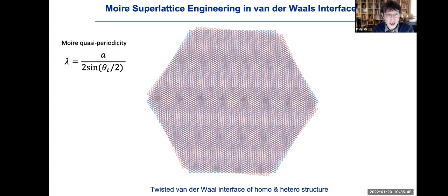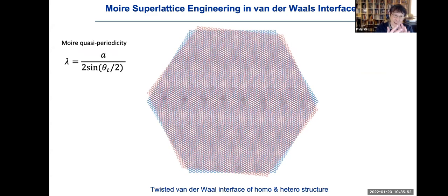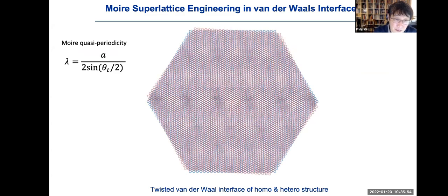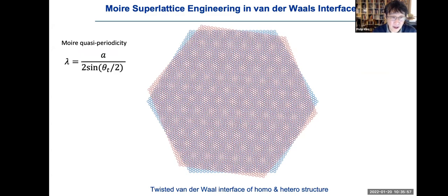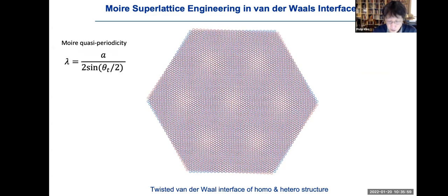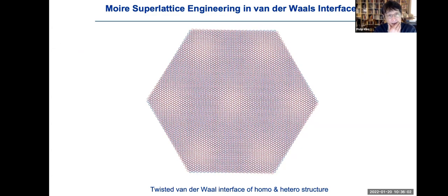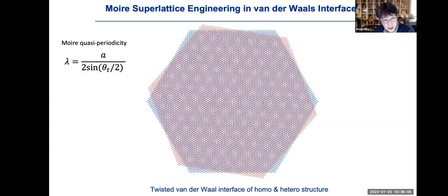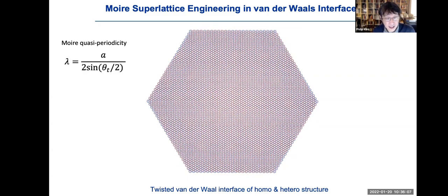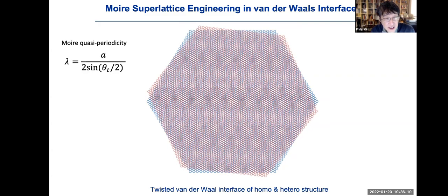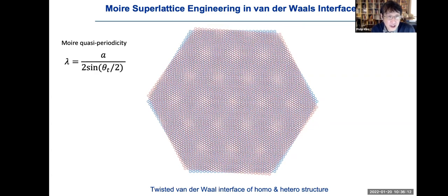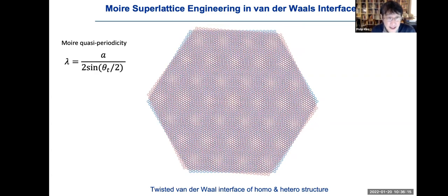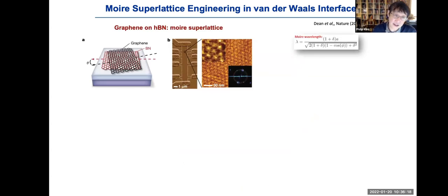This is the so-called twisted stacking of the system. As you see here, by just changing this stacking angle, although this is the same material, together they form some sort of quasi-periodic structures, what we often call Moire structures, right? And these Moire structures can be controlled by the stacking angle, and that's a way that we can engineer additional periodic structures larger than the atomic length scale. In fact, this type of Moire engineering has already been used several years ago. For example, graphene on top of boron nitride, again very similar materials, forms these Moire lattice structures.